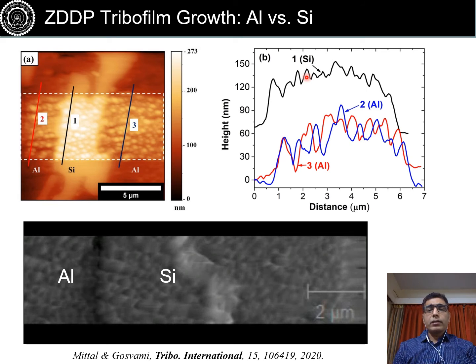And again we could relate it to the stresses because silicon is a much harder phase compared to aluminum. So the contact pressure for a given load at which we are sliding, the contact pressure on silicon will be much higher. That will result in a faster rate of reaction, and that will grow a thicker film. That's what we believe based on our observation we had earlier on ferrous substrate where stress had shown strong relation to the tribofilm growth rate, and on aluminum, which is a softer matrix, stresses are significantly lower, and that will result in thinner film.